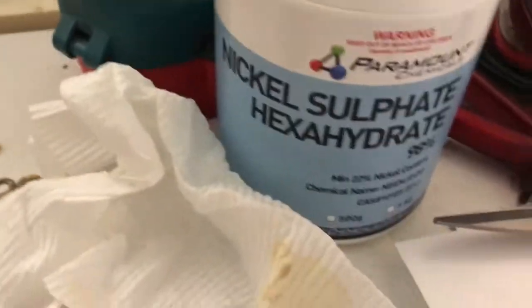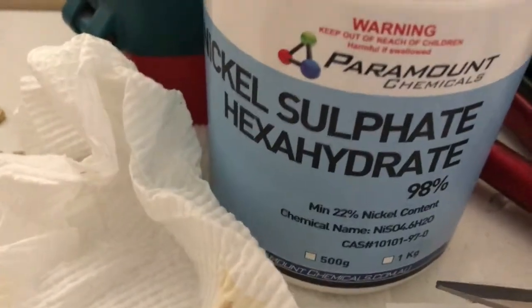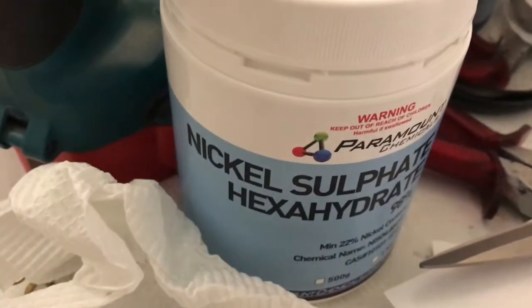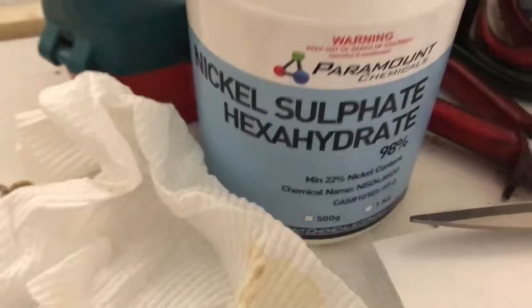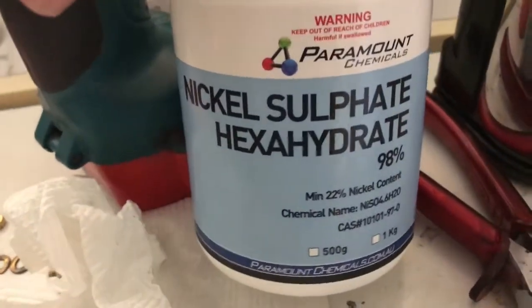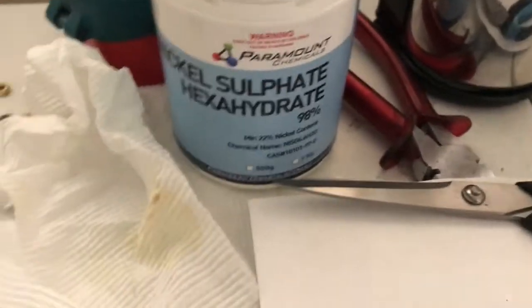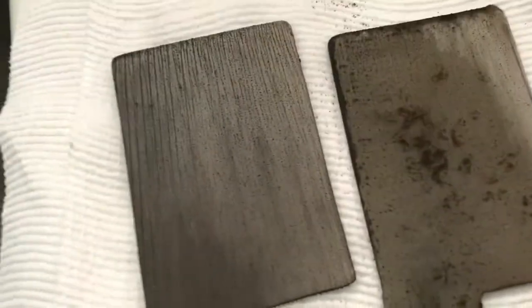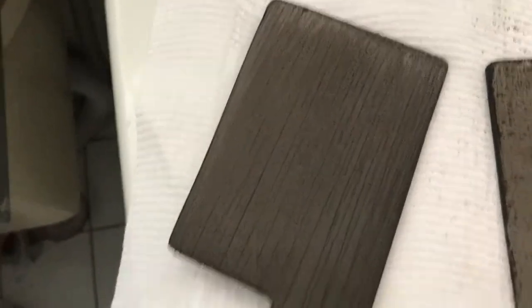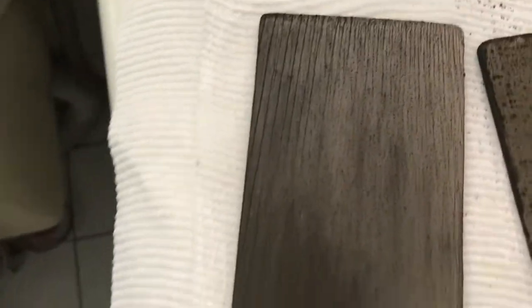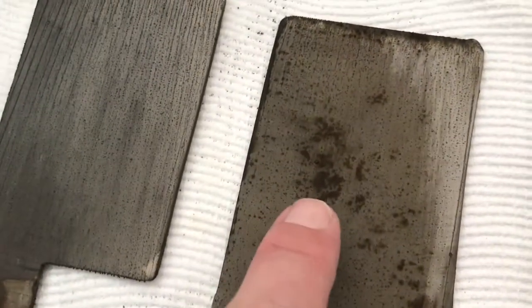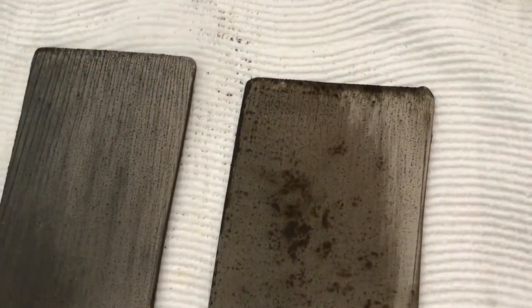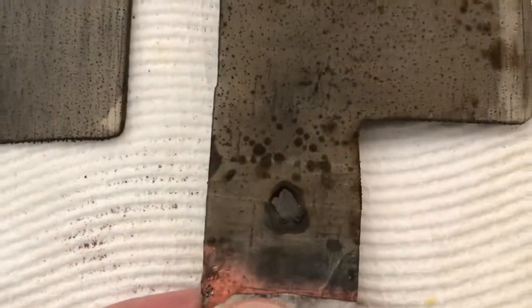I just got my new nickel sulfate hexahydrate. And the other one was ammonia and nickel sulfate. So this one doesn't say anything about ammonia being in it, so I'm going to give this one a try. The negative electrodes plated with nickel, 1 hour each side. This one turned out not too bad looking, but it's just come out of the electrolyte. That one's been sitting for 2 hours outside. So got some of this, probably some copper coming through from the plating process and being in the electrolyte, I think.